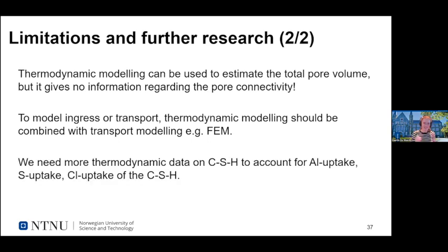And then finally, the further research. What I tried to show with the chloride binding example is that we need more thermodynamic data on CSH. In all the examples I've shown, you see that CSH is the main hydrate. Currently the model doesn't account for aluminum uptake, sulfur uptake, and chloride uptake in CSH. And as it's the main hydrate, small variations in uptake of these elements will affect a lot the hydrate assemblage you predict. So I want more work on that, and I'm in for it.